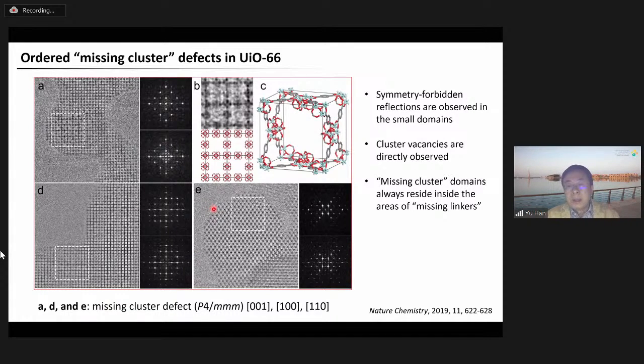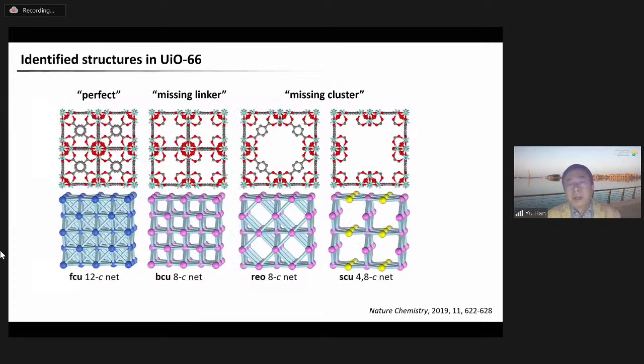And we found that in comparison with the missing linker defects, the missing cluster domains are usually much smaller, only across a few unit cells. And these missing cluster defects always appear along with the missing linker defects. So we totally identified 3 types of defects in UiO-66.